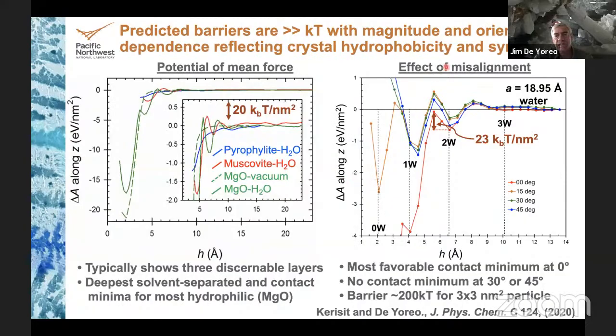Okay, you can also see the effect of misalignment. So if the particles are perfectly aligned, they have a deep minimum and they have a sizable barrier. As you start to misalign the particles, you lose this minimum, becomes less likely that the particles will come together. And in fact, for 30 and 60, 45 degrees in this magnesium oxide system, there is no primary minimum. But look at the heights of the barriers. This arrow is only 23 kT per nanometer squared. And that means that for a particle that's only 3 nanometers on a side, the barrier to contact is 200 kT. And so it seems like oriented attachment is virtually impossible in such systems. So the question is, how do we actually get oriented attachment?